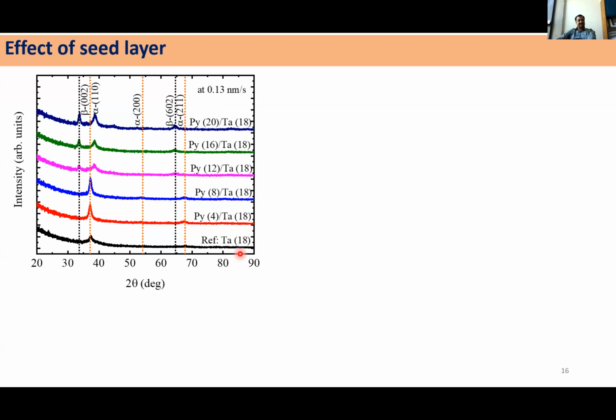Now the interesting thing that we have observed is that this is the reference tantalum, which means the tantalum that is deposited on silicon. But when we deposit the same tantalum on top of a seed layer, that is permalloy of 4, 8, 12, 16, and 20 nanometer different thicknesses, interestingly, for the same growth rate, that is 0.13 nanometer per second, you can see that the tantalum deposited on 4 and 8 still shows the alpha phase, similar to the reference sample. However, tantalum deposited on permalloy 12, 16, and 20 shows a nucleation of beta phase. So the tantalum deposited above 8 nanometer shows mixed phase, and up to 8 nanometer shows the pure alpha phase.